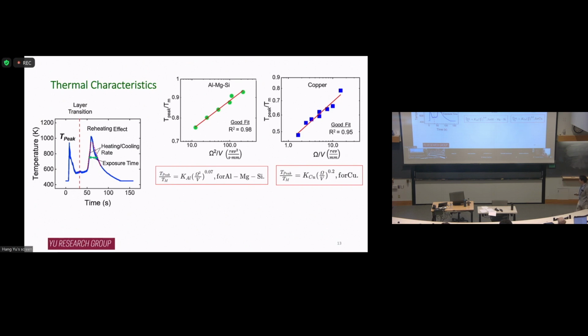So anyway, I think the take-home message is we can have a pretty extensive measurement of the thermal features during the process, and we generally can make the following conclusions. To ensure good deposition quality, the peak temperature needs to be high. It's below the melting temperature, but generally it's in the range of 50% to 90% of the melting temperature. Okay? The exposure time, meaning how long the material is under elevated temperature, is usually on the order of 10 seconds for typical deposition. Of course, it depends on what material and what condition you want to go.